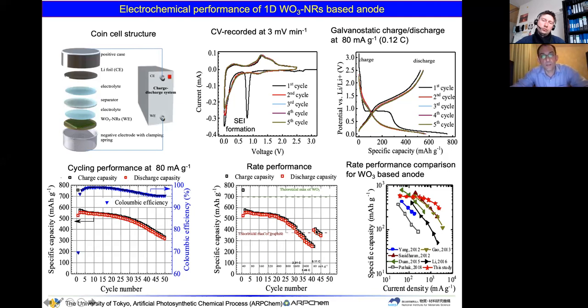So what does it mean? It means that if we choose appropriate C rate for the charging and discharging, so actually we can save the lifetime of this material. So this means that, for example, it's depending how fast we want to charge this battery, 5 minutes or 10 minutes. So actually, you see, this is really a unique material.